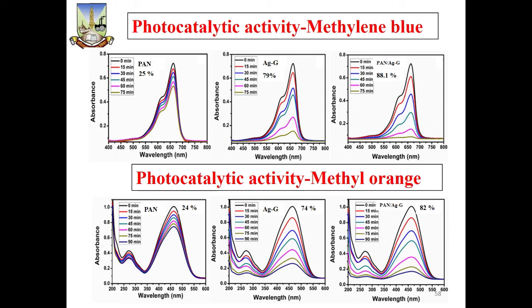We have used different forms of that particular material: pure PAN nanofiber, pure silver grafted nanoparticles, and PAN AGG nanofibers for the degradation of methylene blue. PAN itself shows 25% degradation of methylene blue, the AGG shows 79% degradation, but PAN AGG nanofibers show 88.1% degradation of that particular material.